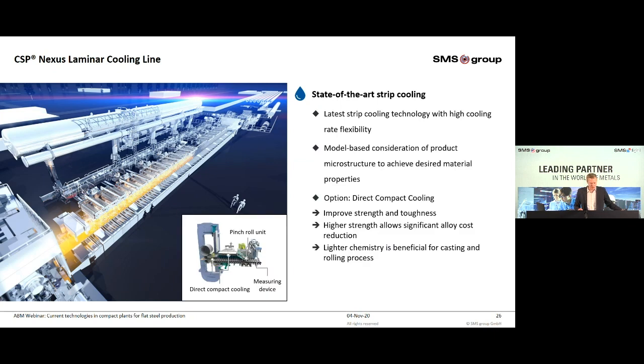The next slide shows the laminar cooling line of the Nexus plant. The latest strip cooling technology is installed and allows a wide range of settable cooling rates. High cooling rates improve the strength and the toughness. Higher strength allows a reduction in alloying costs. Low cooling rates are needed for soft grades with higher formability, for example, deep drawing and extra deep drawing grades. The cooling rates are controlled by a process model to achieve the desired material properties.